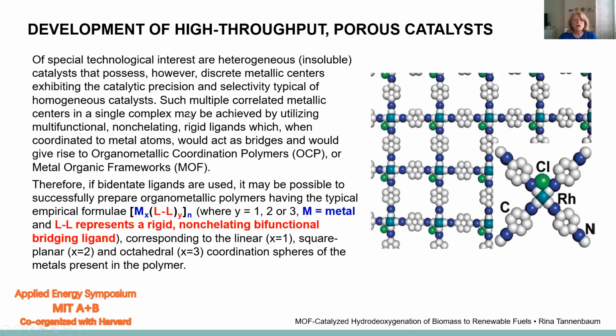And so the idea to increase the exposure of metallic centers, of the catalytic sites, as much as possible to the substrates can be achieved by having a catalyst that is actually highly porous. And so such multiple correlated metallic centers in a single complex are going to have homogeneous qualities, being held in a heterogeneous overall complex without being tethered, but being an integral part of the complex. And so there's no leaching possible.